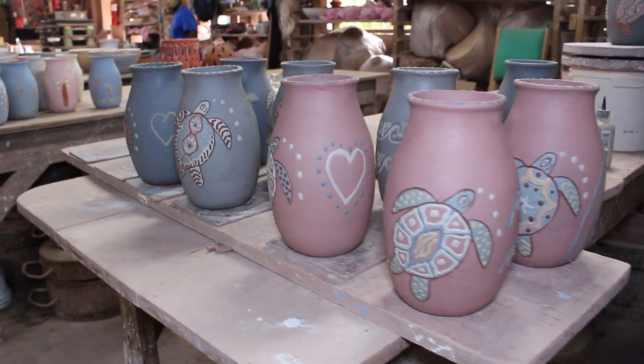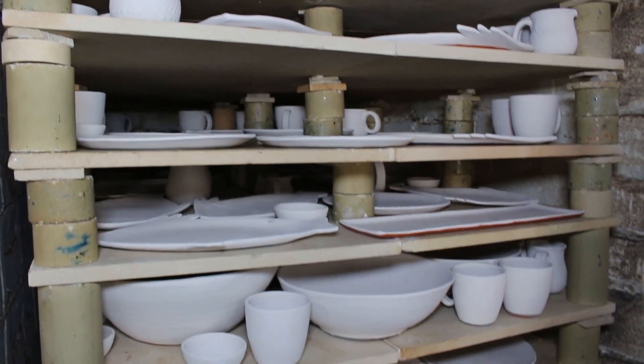When it's fully dry, it will go into a kiln load of pieces along with everybody else and be biscuit fired. The biscuit fire is a low firing which takes you to a mere 1,900 degrees Fahrenheit or 1,060 degrees centigrade.